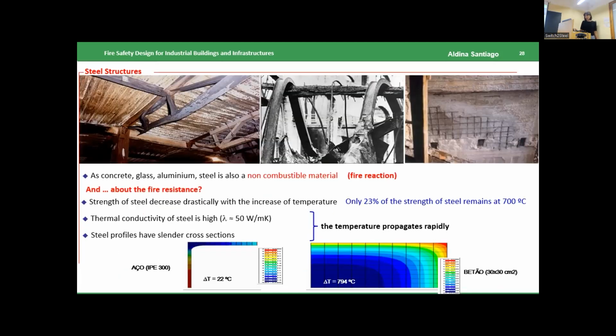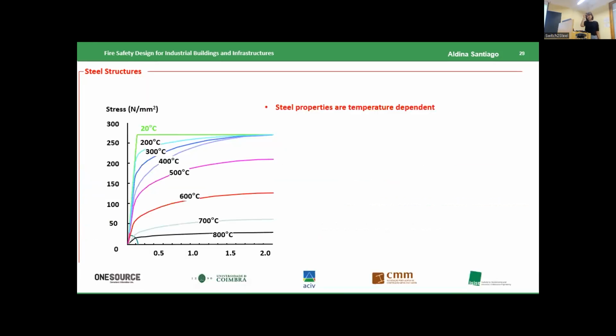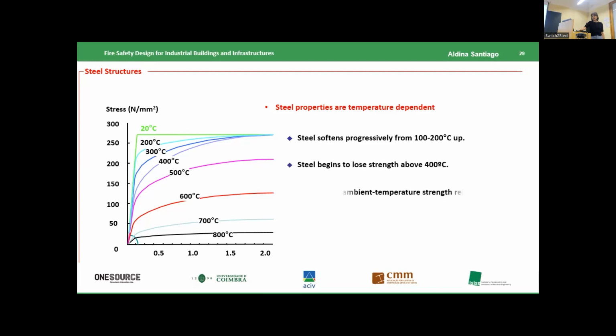I put here to show, as I said before, that the strength of steel degrades very fast. Here are the curves of the degradation of the properties of steel with the temperature from 20 degrees to 800 degrees. I have some notes. The steel softened progressively from 100 to 200 degrees up. The steel began to lose strength above 400 degrees. Only 23% of ambient temperature strength remains at 700 degrees. At 800 degrees, strength reduced to 11%, and at 900 degrees to 6%.